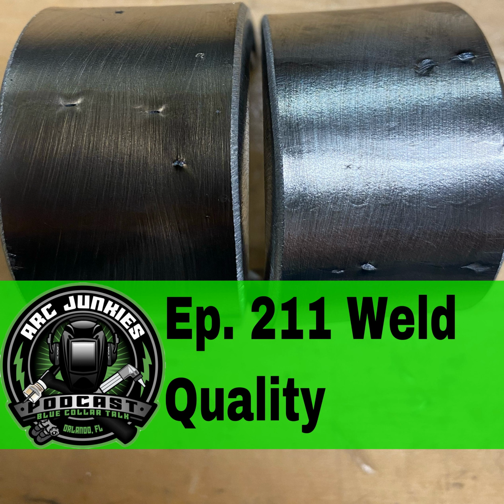We can't travel too fast or too slow, because an increase or decrease in speed is going to result in different welding discontinuities. We want to try to avoid those. Incomplete fusion can also be caused by a travel speed that's too slow, because now we're putting too much filler metal into that material, and it's not allowing it to melt into the base metal properly. So travel speed too fast, travel speed too slow, these can both lead to incomplete fusion.